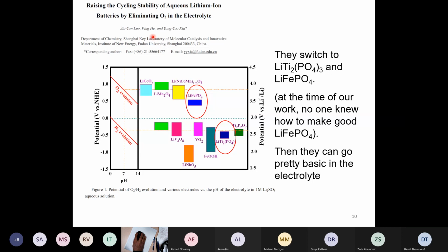Yeah, so this is a paper, unfortunately the year isn't shown. It was relatively recent though. And what happened here was these guys decided to use lithium iron phosphate as the positive. And you can see that it's quite a bit lower than lithium manganese oxide spinel. And then they used lithium titanium phosphate as the negative side. So, when we did our work on the aqueous battery was 1994. No one knew that lithium iron phosphate was useful until 1997, right? So nobody knew that LiFePO4 was going to be decent. And anyway, with these two choices, you can move to a pretty basic electrolyte. You can work relatively basic here if you want.